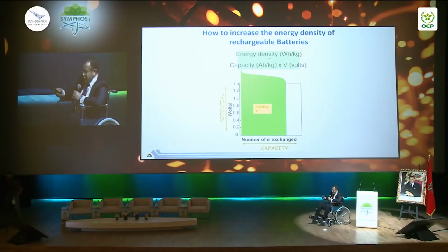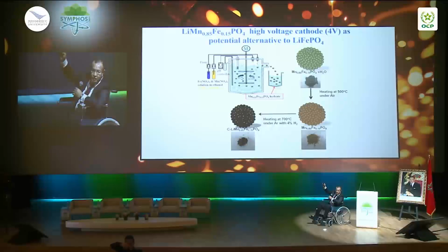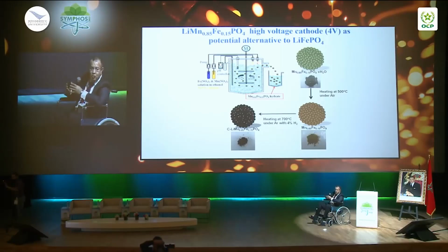Fortunately, there are many other phases of phosphate that have high voltage. One of them is manganese phosphate. Manganese is still a cheaper metal. As you can see here, it's a 4-volt system. So now you jump the voltage by 0.5 volt and you increase the energy significantly. And you can do the same process to make dense nanopores type material.